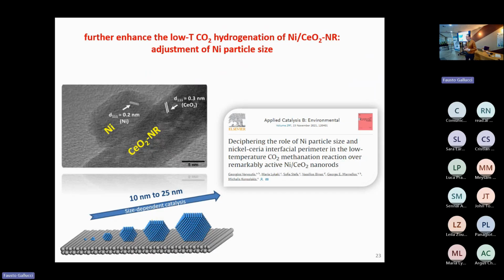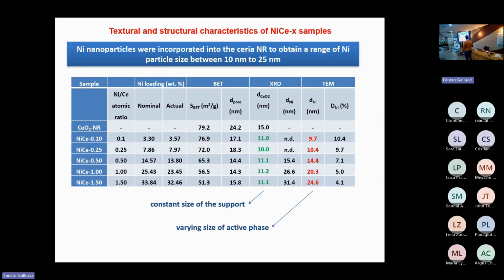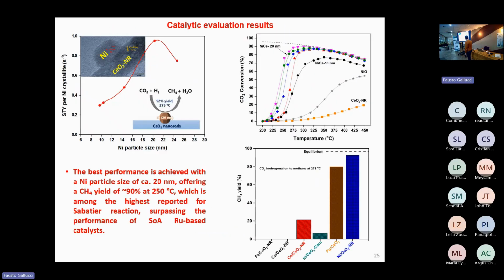Very recently, in an effort to further enhance the low temperature methanation performance below 300 degrees Celsius, we try to adjust the nickel particle size. Thus, we incorporate nickel nanoparticles into ceria nanorods in order to obtain, as you can see here, a range between 10 to 25 nanometers.